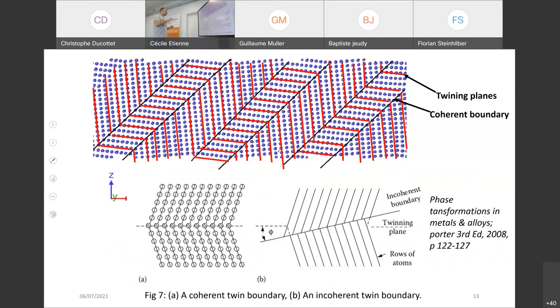Let's now zoom in the first region and see what this structure is. What you can see in this first region here, we have the red planes which represent the twinning planes. These steps are the fingerprints of the twin planes formation. Here you can see the atomic row which represents the coherent boundary. I'm saying coherent boundary because according to the literature, A corresponds exactly to our case. There is no mismatch between the two rows, and it's like a mirror effect. We have HCP phase twinning planes in different directions, and they are coherent.